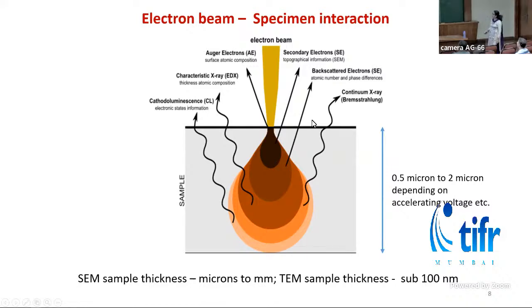Secondary electrons are low energy electrons, which give us information about the sample topography and morphology. Backscattered electrons come from within the sample, and they give us information about the elemental contrast, that is Z contrast, in the sample. So they are used for Z contrast imaging.